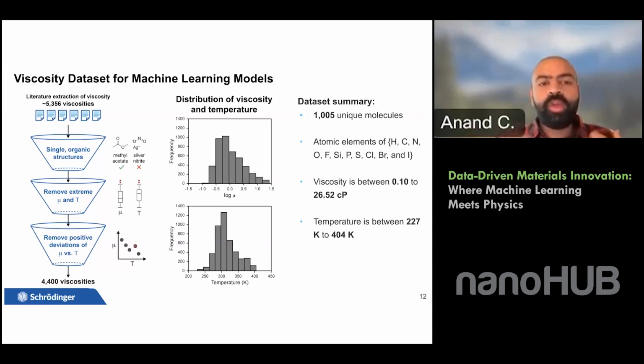We removed any extreme values of viscosity and temperature, because we're trying to make a viscosity model to predict the viscosity of any molecule at any given temperature. As you include more and more extreme data, like if you have an outlier at 1000 Kelvin, your machine learning model is not going to be great. Since we collected data from multiple literature sources, in some cases there's a positive deviation of viscosity with respect to temperature, because of mismatch between different sources. So we made sure to remove any positive deviations, since viscosity should be decreasing with temperature for molecules in general, and made sure that the data set was consistent.